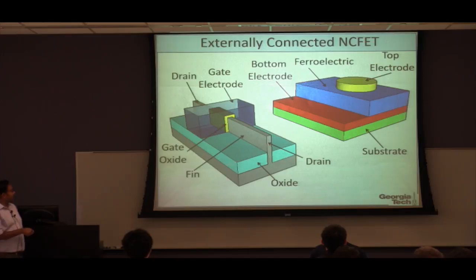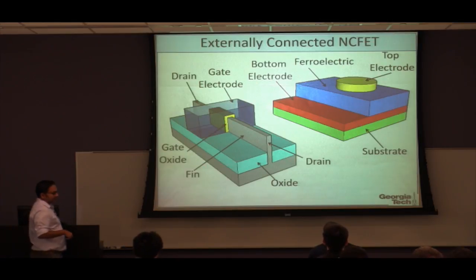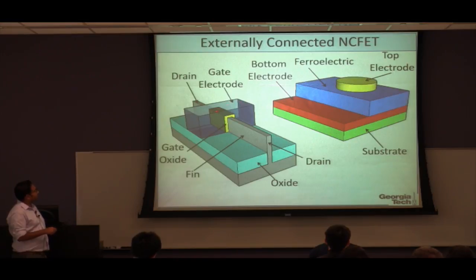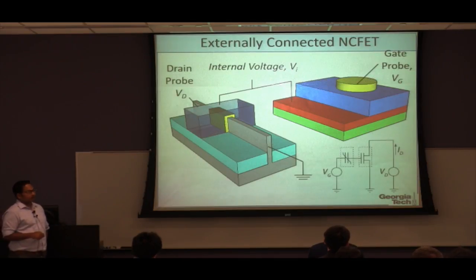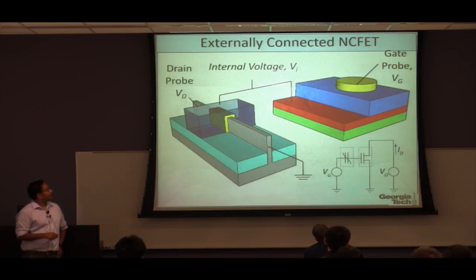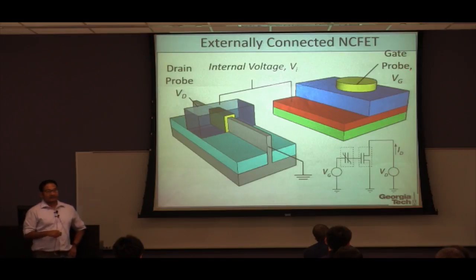We took a FinFET device. This is the fin of the device in this schematic diagram, and this is the gate oxide, gate electrode. And then we again took another capacitor, which is ferroelectric. And then what we did was we made a simple connection. We just connected one side of the ferroelectric to the gate of this FinFET, and then use this terminal of the ferroelectric as the gate.